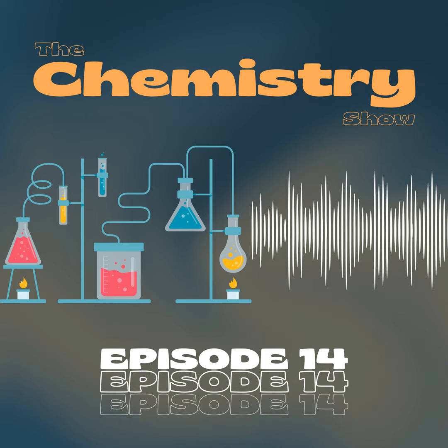Well, we can manipulate the pH of the solution. The pH? Yeah, that changes the charge on the support surface. And that allows us to select which ions get attached. So it's not just about attracting any ion. No. We can be selective. Precisely. And this level of control is incredibly powerful. So we can tailor the composition and distribution of those nanoparticles on the support. Exactly. And that can have a huge impact on their catalytic performance. This is starting to sound like a very versatile technique.